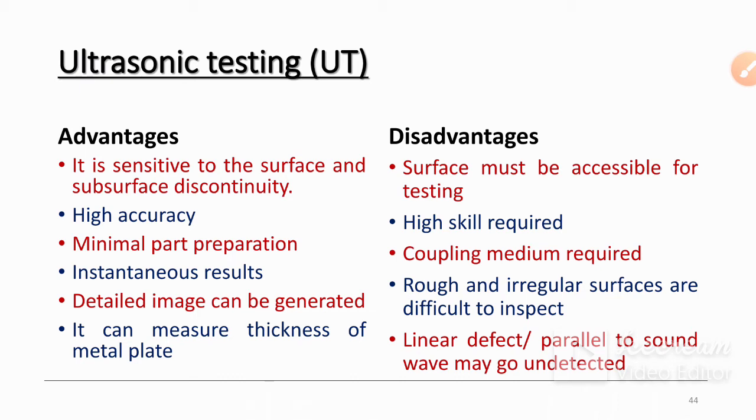Linear defects parallel to the sound waves may be undetected. For example, if there are some vertical cracks, it is difficult to find the ones which are parallel to the sound waves. Okay, for that you need to test the material by rotating it 90 degrees.